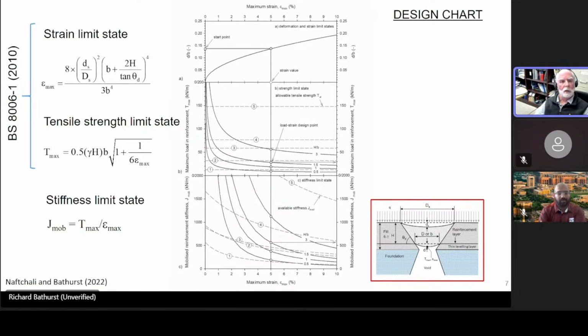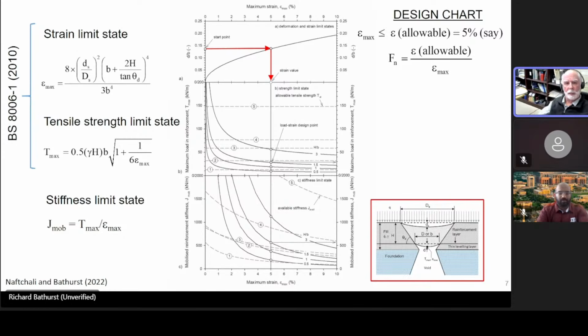So one starts at the top figure with an assumed allowable strain in the reinforcement, and this will define the ratio of the deflection, the vertical deflection at the base of the reinforcement to the width of the void. So one comes across this chart, and you can relate the geometry of the deformation, if you like, to the allowable strain. And here you see the equation. Typically we like to keep the strain in the reinforcement to 5% or less.